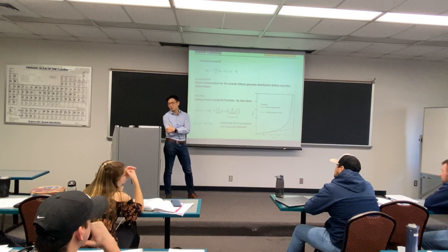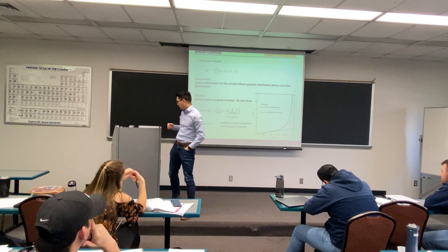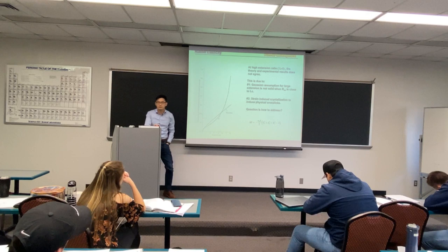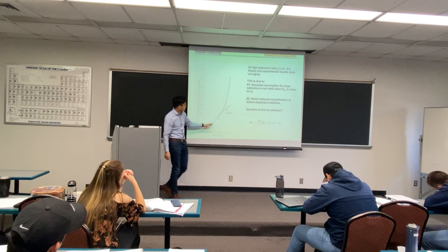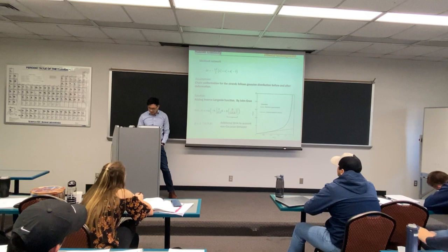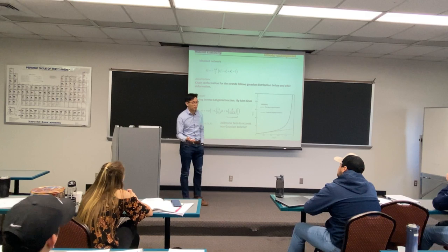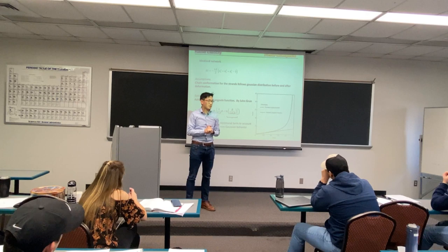So this idea is quite straightforward, right? You just added a modification term mathematically that can help you capture what is going on in the later stage of the increase in stress, basically as you can see in this part. It's an empirical approach to make them agree. Why do I say that? Because this is not coming solely from deviation from the Gaussian chain. As we said, crystallization also happens in this stage, but it's not a constant. However, empirically it works pretty well, so this particular relationship has been quite popular in describing rubber elasticity at high degrees of strain. So just to make sure you understand conceptually how people modified the theory so that it can agree with a broader degree of deformation.